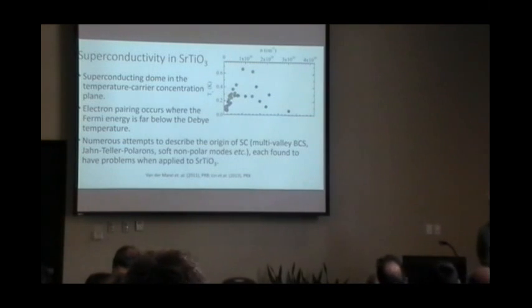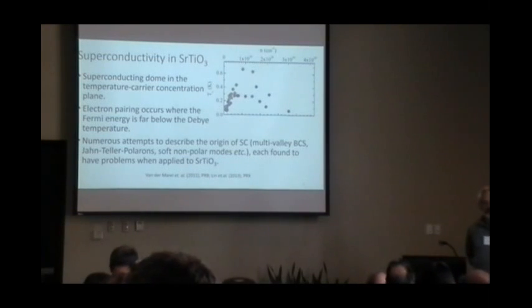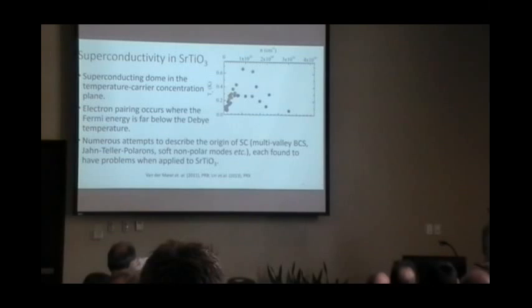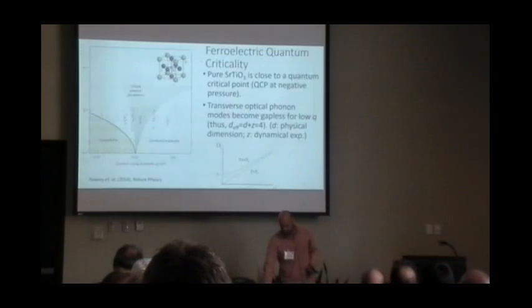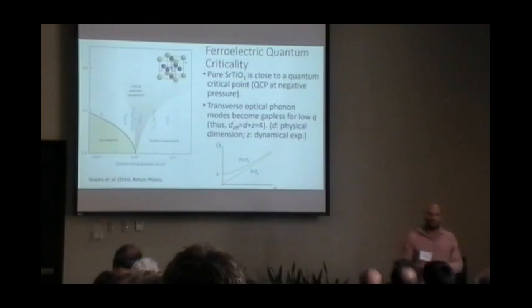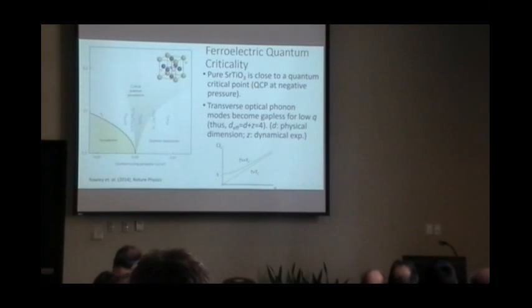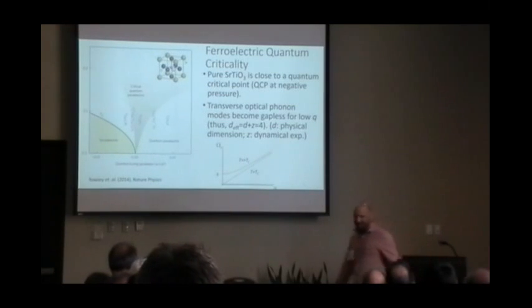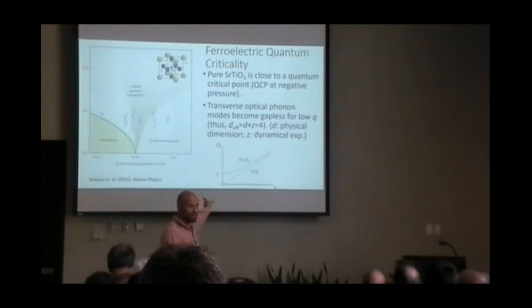Is this the same system for which Balatsky and Spaldin and others were predicting a large isotope effect, a large increase in TC with oxygen substitution? Yeah, the same. Have you looked at that? That's the prediction, but we didn't show TC going in that direction. They suggested to do that. It's very complicated to make these crystals, of course, so we didn't do that yet. But this is what you would expect: if you substitute the oxygen, you go closer to the quantum critical point, and you would expect a higher TC.